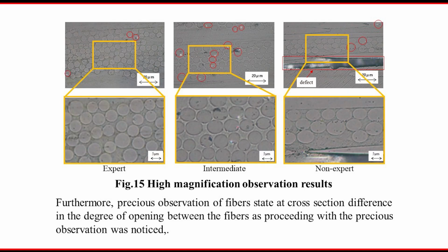So why can this difference occur between the expert, intermediate, and non-expert? Until now, we have data about the void around the filament. The expert void content is very low, and the non-expert void content is very large. And then we checked the fiber state, the filament state. Precise observation of the fiber cross-section shows a difference in the degree of opening. Opening means that when a filament and the next filament contact each other, we do not say it is open.